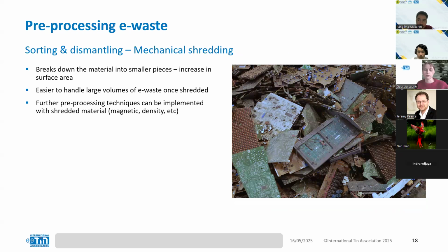An alternative route to go down is to start by shredding the PCB material. If recycling companies want to target more metals and go down a different route to bulk recover metals from PCBs, they can start with techniques such as shredding the material. The perks of shredding the material is reducing the volumes of e-waste, making it much easier to handle as it can be condensed. If we were to place a lot of PCBs into an acid bath or into a furnace, if the material is shredded up and condensed, it's a lot easier to fit more material into the furnace or the acid bath.